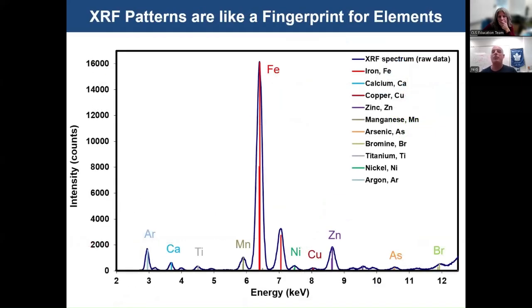When we looked at powder diffraction patterns, we talked about how a good way to think of a powder pattern is that it represents a fingerprint of the different crystalline compounds in the sample. An X-ray fluorescence pattern is like a fingerprint for the elements in the sample. The different peaks in the pattern correspond to different elements. So this is an XRF pattern for an environmental sample. The largest red peaks in this pattern are due to iron, and there's a fairly large peak for zinc, shown in purple. And then there are some smaller peaks for other elements like calcium and titanium and copper and arsenic. So this pattern is like a fingerprint for all the elements in our sample.